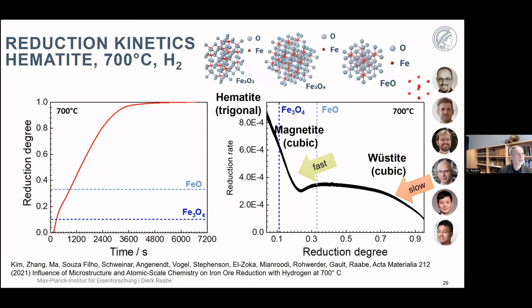Now, when we look at such a reduction kinetics, and I take here hematite as a reference, we take 700 degrees centigrade, that is relatively moderate in terms of temperature, to track the processes a little bit more in detail. And then when you look at the reduction rate as a function of the reduction degree plotted here, you go through different phase transformations. So you start with the hematite, which is a trigonal crystal structure, and transform first, under, of course, extraction of the oxygen, into magnetite, which is an inverse spinel, a cubic crystal structure. And then you go from the spinel very slowly into the wüstite, and that transforms very slowly into body-centered cubic iron at this temperature. The wüstite is a cubic sodium chloride type of structure with, again, less oxygen compared to the magnetite because you are gradually removing the oxygen out of the structure.